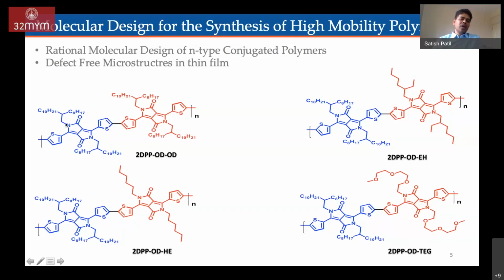And we introduce these alkyl chains to make the polymeric material soluble in common organic solvents. When you compare these structures with the other chemical structures, here we varied the alkyl chains. By varying the alkyl chains, we wanted to study what microstructures these polymers form. First, the idea is very simple here. You have to have a large delocalization length in the polymer. Then we improve the microstructures, improve the crystallization of the polymer, by introducing different alkyl chains.